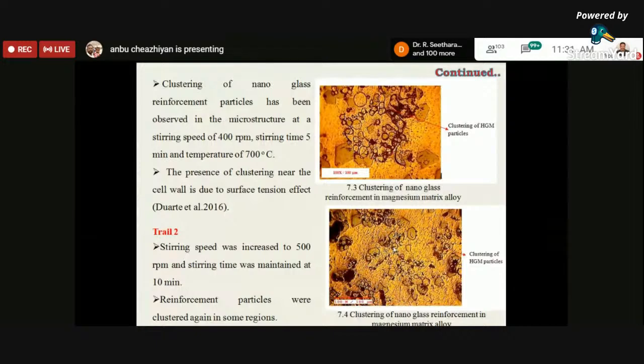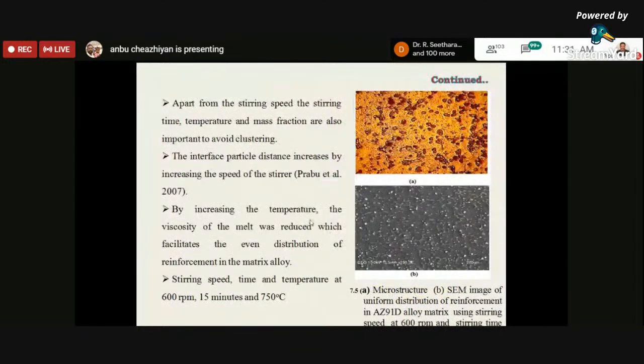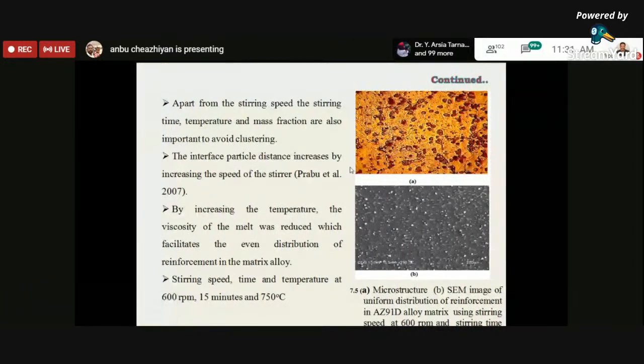It is also noted that apart from stirring, the temperature and mass fraction are also important to avoid clustering. The interparticle distance increased by increasing the stirring speed. So from that, we increased the speed to a maximum of 600 rpm and made it 15 minutes stirring time. The temperature of the melt was increased to 750 degrees centigrade, and it was cast. From that, a maximum uniform distribution of reinforcement particles was obtained in the matrix alloy.